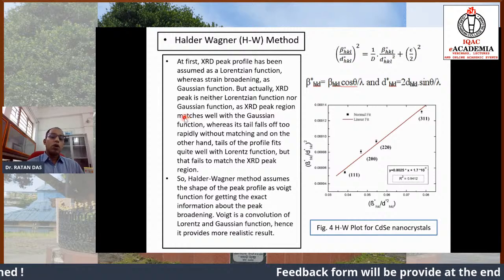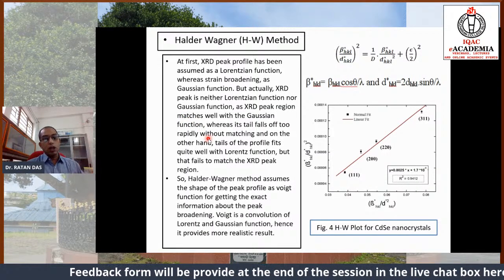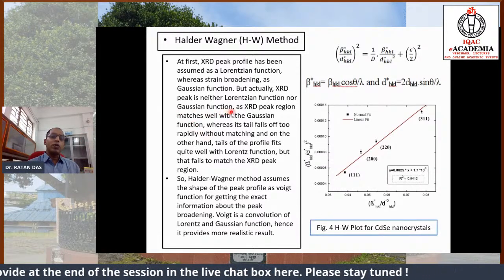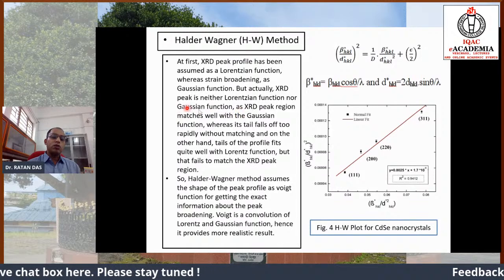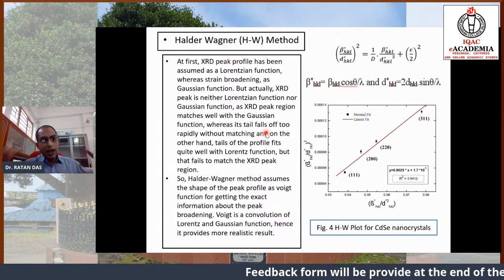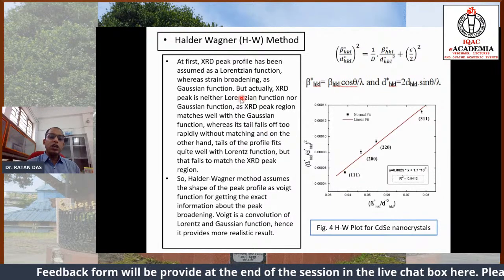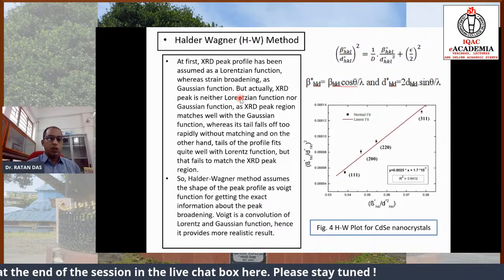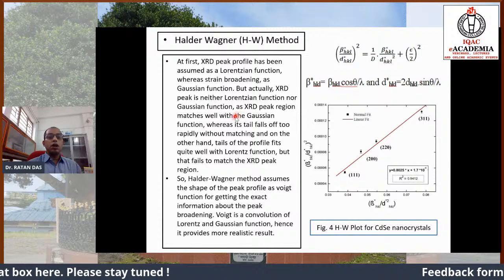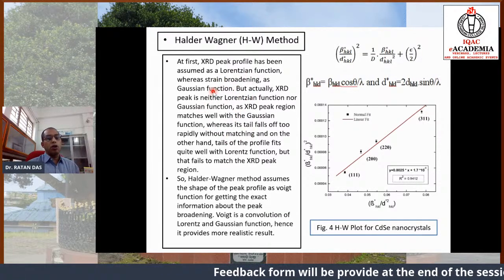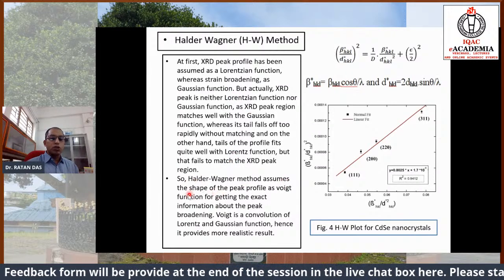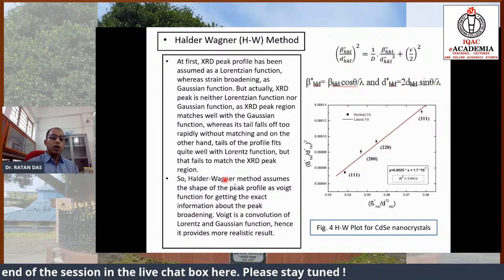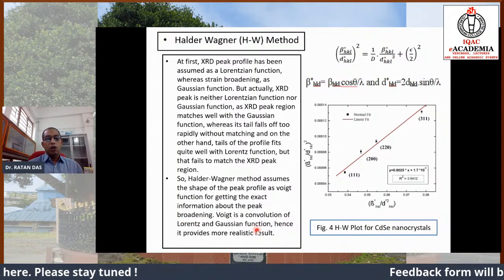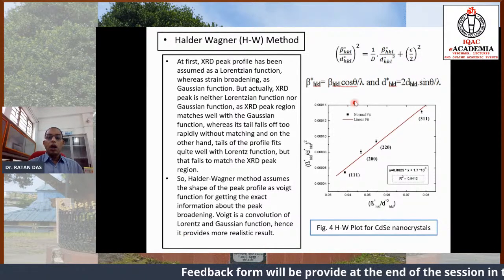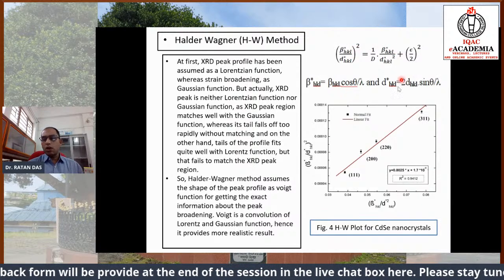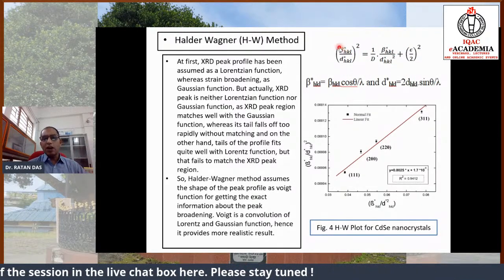Generally we observe that in one particular XRD peak, if the peak is very smooth, then a Gaussian pattern may be associated. But with a Gaussian pattern, if the peak position matches, the tail may not match. For a Lorentzian function, the tail matches, but the peak does not. So we generally take a mixture of Lorentzian and Gaussian functions. The Halder-Wagner method assumes the peak profile shape as a Voigt function, which is the convolution of Lorentzian and Gaussian functions and gives a more realistic result. There is a complicated formula, and every term is known.